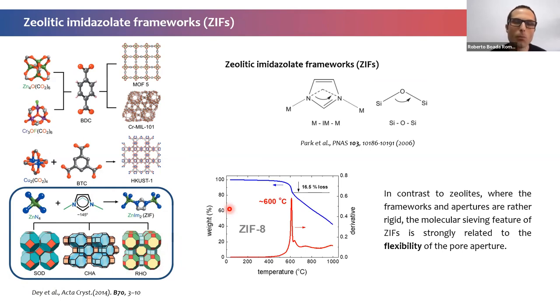One of the benefits of these materials, when we compare with traditional MOFs back in the day, is that one of the difficulties of those MOFs was that they could not stand high temperatures, so they were not chemically resistant. These ZIFs, in particular the one we are going to discuss today, ZIF-8, which is this structure here, the sodalite structure, are more resilient in terms of temperature and chemical resistance, which is quite good. However, in contrast to the zeolites, the ZIF frameworks do not have such a rigid structure, okay? And we will see how this behaves in terms of gas adsorption and gas permeation.